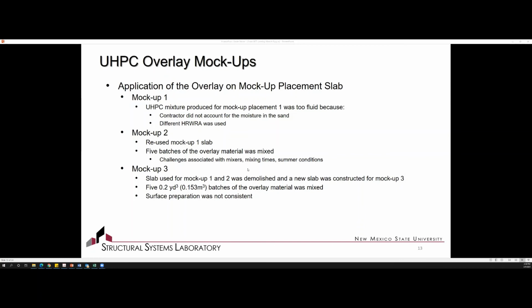And again, we cast 5 batches of the overlay material. And in this case, we did notice that the separate surface preparation wasn't consistent again. So we again looked at the bond as we were planning on.